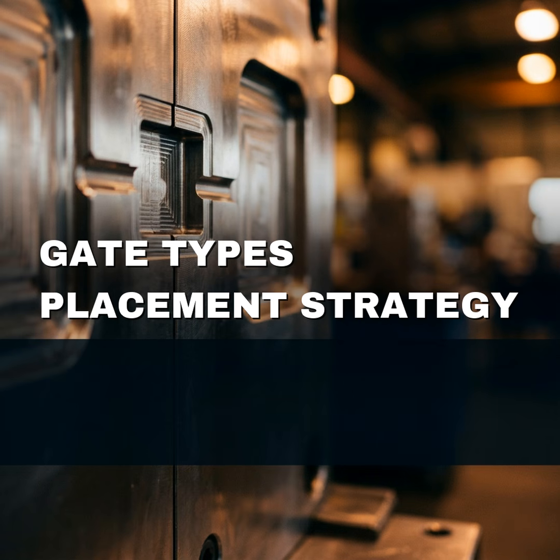Good question, actually. That's where the submarine gate, or tunnel gate, comes in. It's an advancement of the pin gate design. It retains the benefits but addresses some of the complexities. The big thing here is its hidden placement. It's often conical, angled between 20 and 40 degrees relative to the cavity, and can be placed on inner surfaces, sides, or even bars or columns. You can even set it up to be sheared off by the ejector rod.